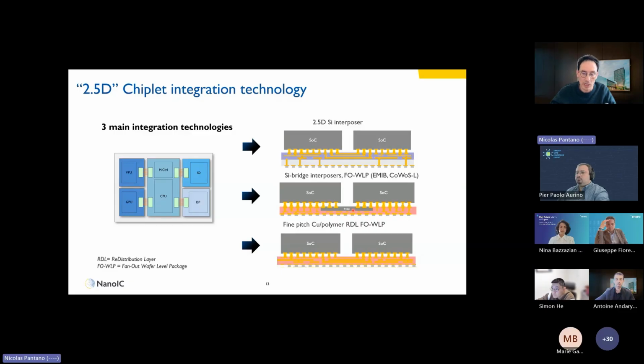The problem, or maybe the challenge with that technology, is that you have to bring one of these bridges inside the polymer. There's a CTE mismatch. That means that they will expand with temperature differently, because one is silicon, the other one is a polymer. And it's very complex when you start to scale the system to many SoC integrated, and you start to have many of these bridges. So Imec has developed a fine pitch RDL process, which is polymer based, that can get to dimensions that you have on a silicon bridge. So you get rid of the silicon bridge, and you have a monolithic organic substrate here.